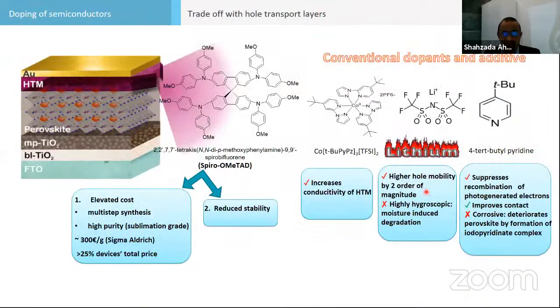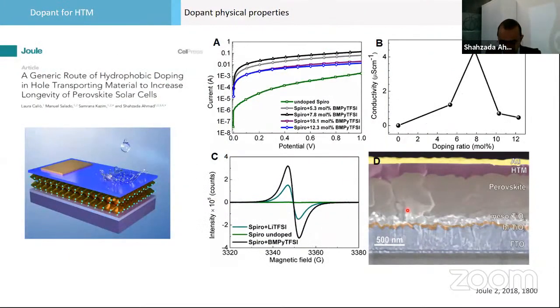Most of the p-type materials use a dopant made of lithium. Lithium, we know, is highly combustible and highly hygroscopic, and this is not very good for stability. So we developed a new type of dopant, which is based on ionic liquid. It was published in Cell Press in June. Ionic liquid is a very stable material, and we got exactly the same, on par performance as the lithium-TFSI dopant. So we are very happy. The good thing is that the devices are much more stable, and we can see the hydrophobicity of the surface is very high.